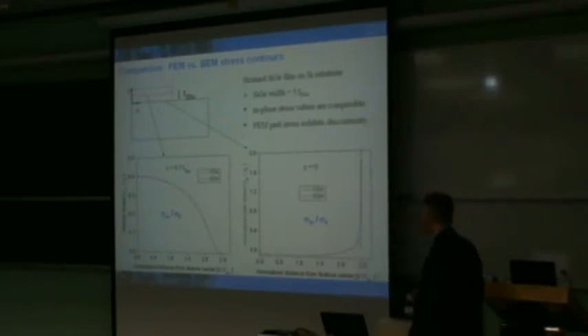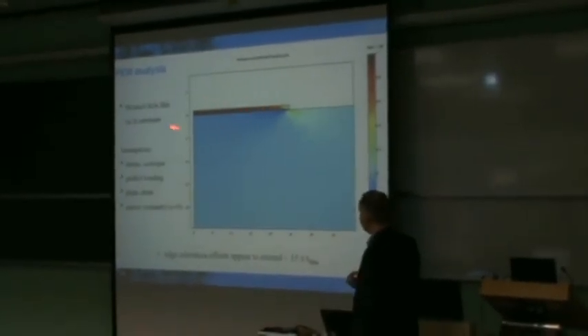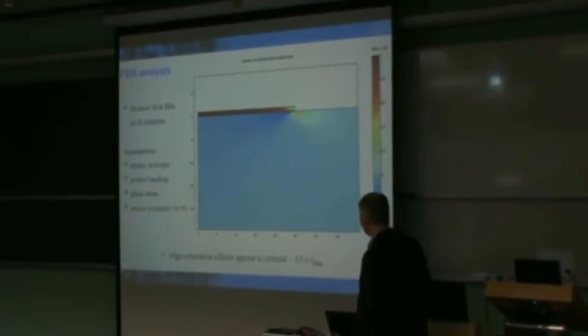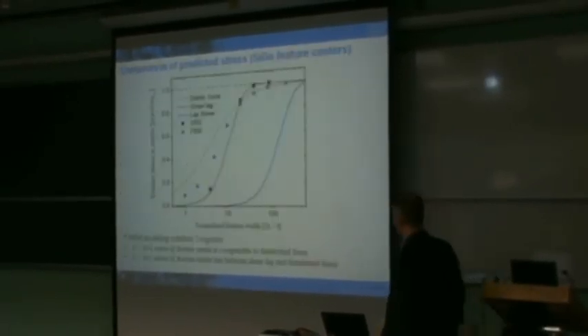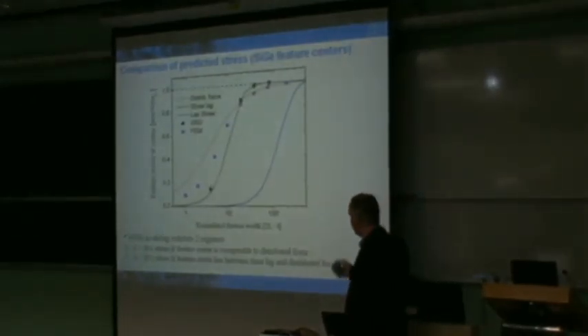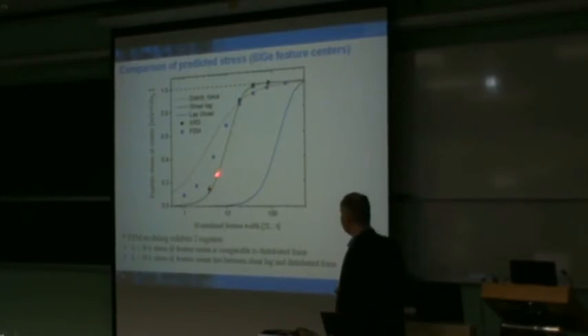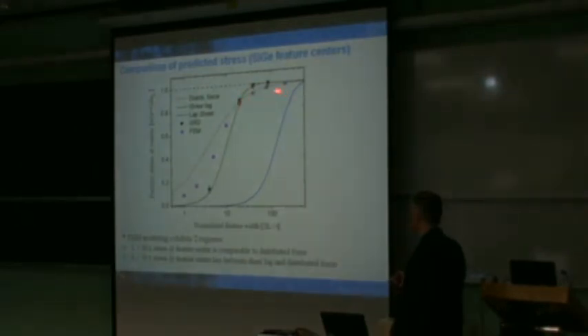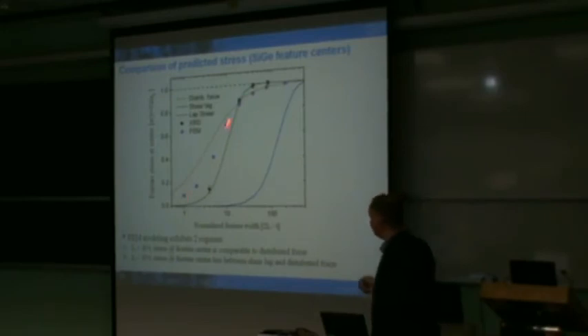So that's just one thing when you're evaluating the merits of these various techniques that exist. And then here's just an example showing the fact that if we do a finite element analysis, this is using COMSOL, we can clearly see the edge relaxation, and these effects can extend, again, fairly far field, 15 to 20 times the film thickness that we have. So now incorporating all those aspects on the same universal curve that I showed before, we can see that the finite element method comes very close to the distributed force analysis. And that is what we would expect for these very large features, because again, we're not impacted by that problem with very narrow features. And as we get down to lower values, we see something that basically spans between the two cases.